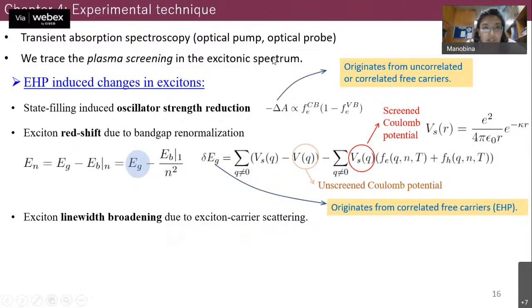So we use transient absorption spectroscopy in optical pump, optical probe mode. And to detect this plasma, we trace the plasma screening in the excitonic spectrum. So now first we need to distinguish between free carriers and the correlated carriers, which is the plasma. So for that we track this oscillator strength reduction, which occurs due to the free carriers, which may be uncorrelated or correlated. And we track the excitonic redshift over time due to the band gap renormalization.